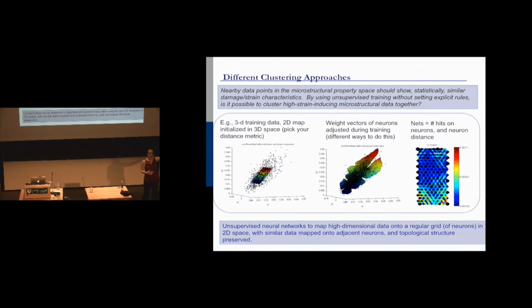The damage one's really easy. I showed you guys those, right? I mean, that's a 2D space already. Red's really bad damage, blue's not. So that one's done. The microstructural one's tricky. So you take that data, throw it into 100-dimensional space, and you change the sliders, or the importance of each variable, until you get it to best match the damage map.